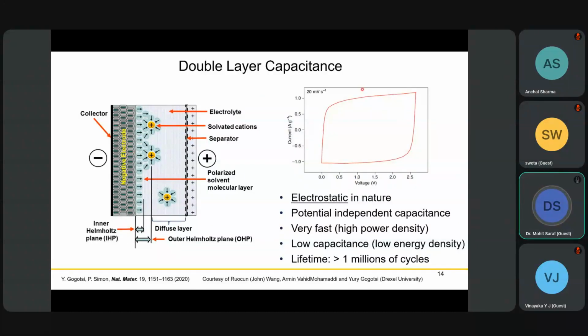So basically you get this double layer, rectangular shape CV curve. Since it is very fast, you can expect very high power density, but it will be limited by capacitance because the charge storage is only on the surface and it is very limited, and that's why you have very low energy density. But since there is no chemical reaction, you do not lose anything virtually, and that is why their lifetime is very high.